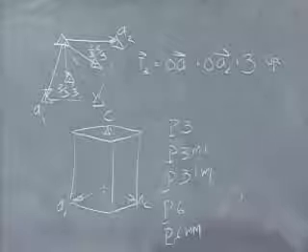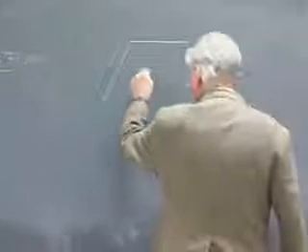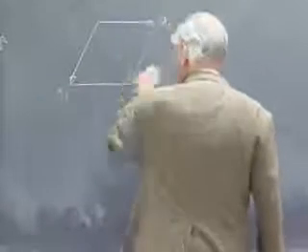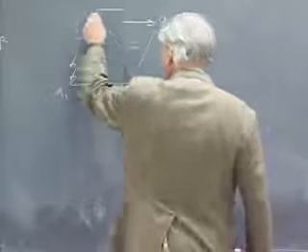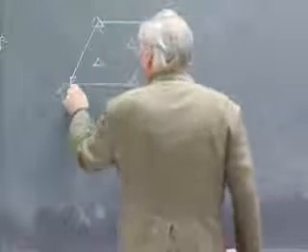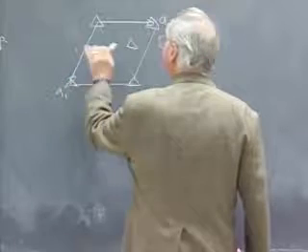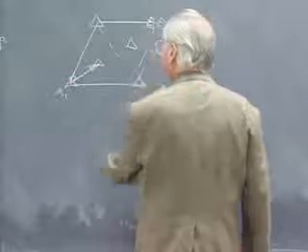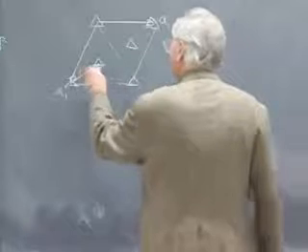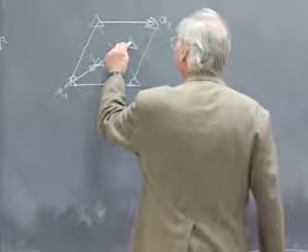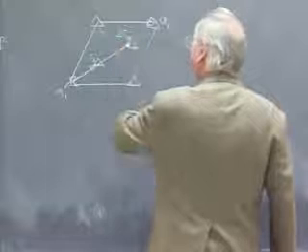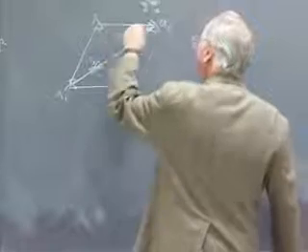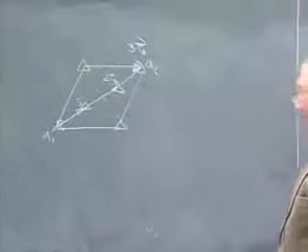And the way that I can show that is, once again, to draw this net. A1, A2. And suppose I pick the part of the offset of T3 that is within the plane of the net as going from this lattice point to this one here. Then if I go twice that translation T3, that's going to put me directly over this threefold axis. And if I go 3 translations T3, I'll be directly over the lattice point on the ground floor.